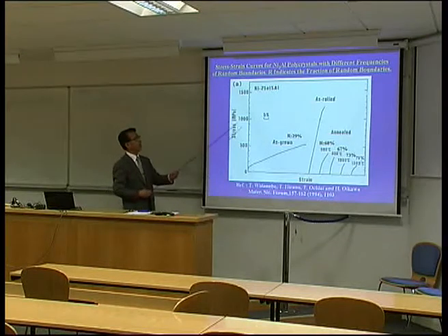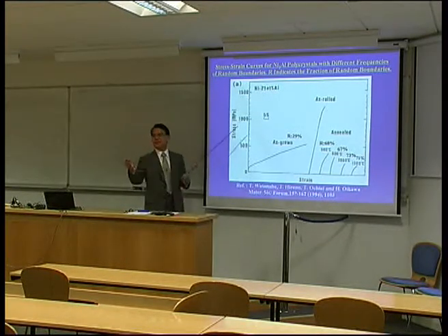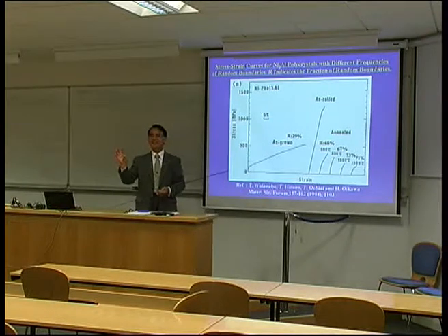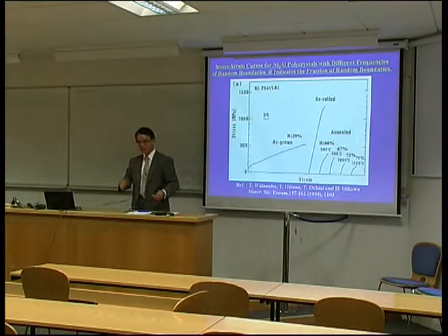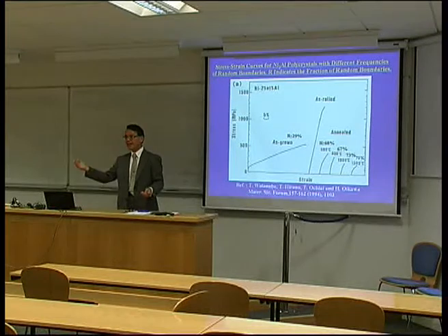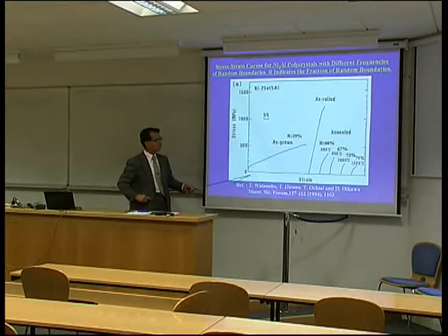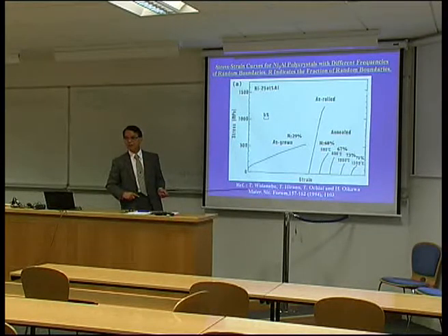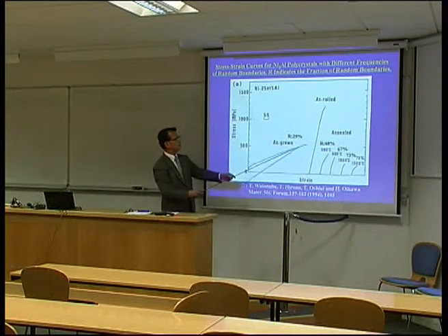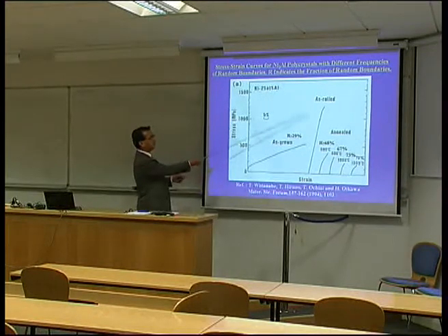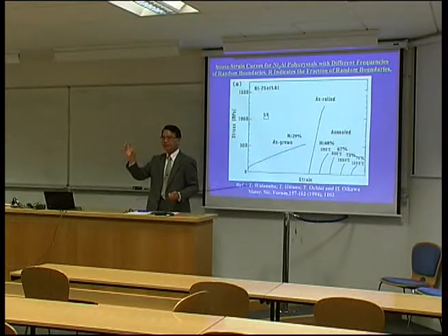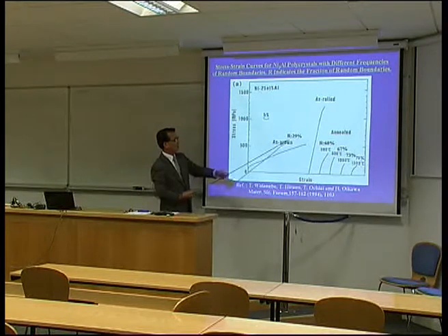Firstly, simply speaking, this is a nickel aluminide, Ni3Al. As you know, this is a very brittle material. Without boron, I think many people in the past thought it was impossible to get ductility. But even without the addition of boron, we can improve the ductility very drastically. At room temperature, without any additional boron, we can get about 50 or 60% elongation.